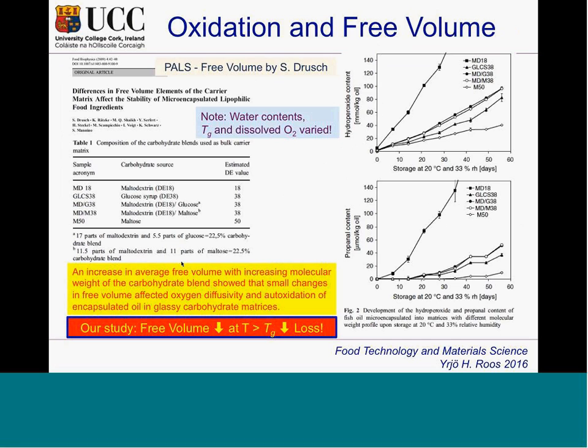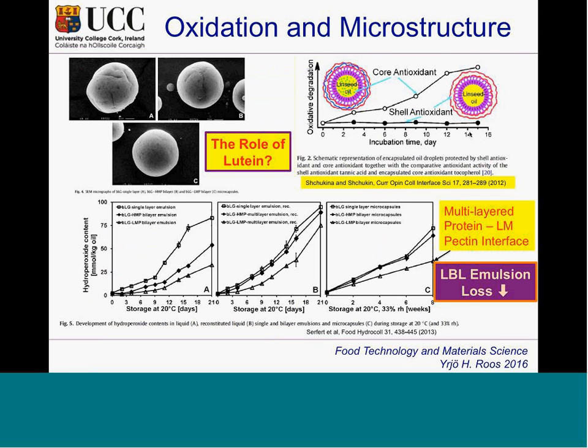The question is the role of free volume in oxidation of lipids in different types of systems. What we can conclude from these studies by Professor Drusch in Germany, in Berlin, is that he has shown that there are more hydroperoxides coming from matrices with big molecular weight than smaller molecular weight. And what we can conclude is that the smaller sugars actually make glasses that have smaller free volumes. And this confirms in our studies what we said about lutein, that it goes to the surface. So actually the antioxidants on the surface act there and stop the radicals or other diffusing components from going into the oil, and that has been shown in the studies as well.